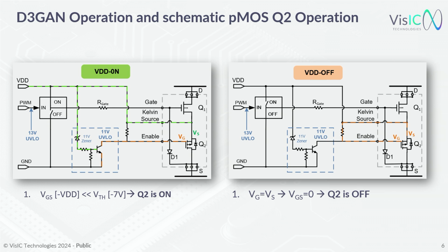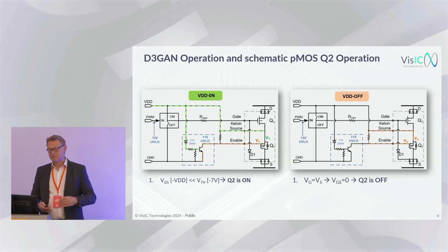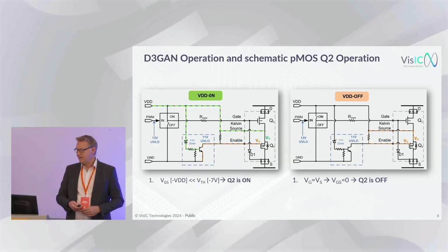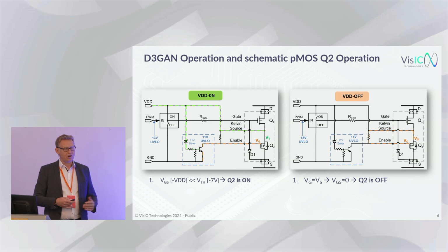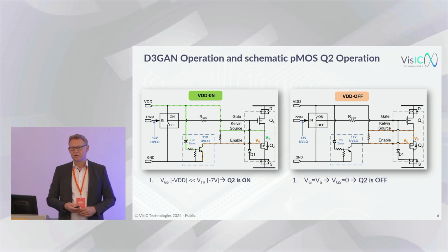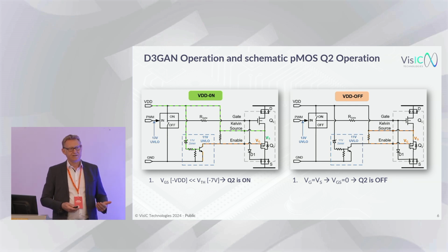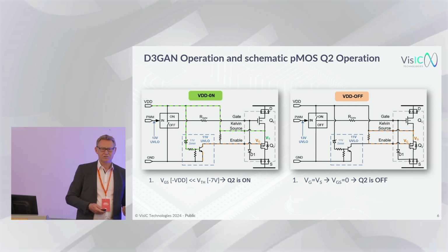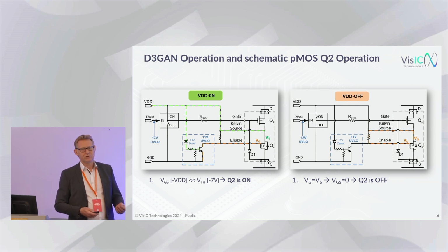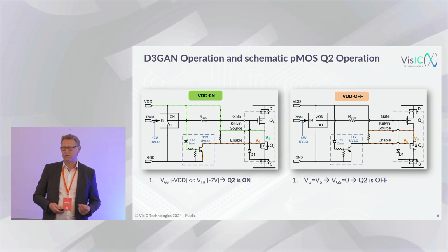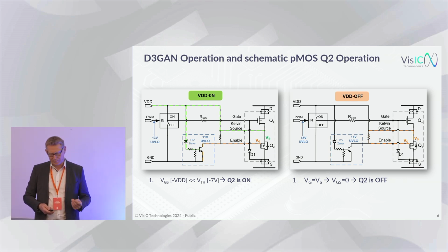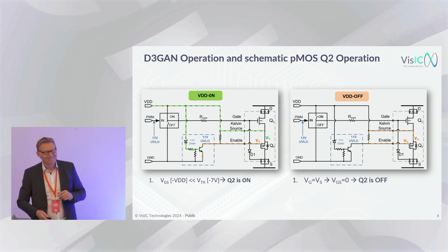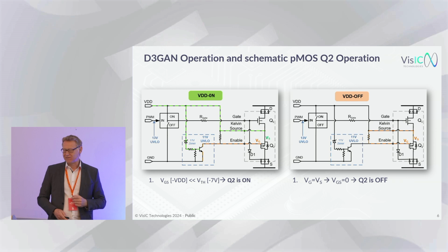In order to do this, we have a very simple gate drive circuitry, which is enabling us with an 11-volt undervoltage lockout circuitry, that the circuitry is enabling the PMOSFET. And then we can switch the device on and off and still having the blocking voltage of 650 volt. And the benefit of having a D-mode GaN is really that we have a very high threshold voltage above 7 volt. That's the beauty compared to an E-mode, which has a very low threshold voltage and which makes it very vulnerable for inductive switching applications.